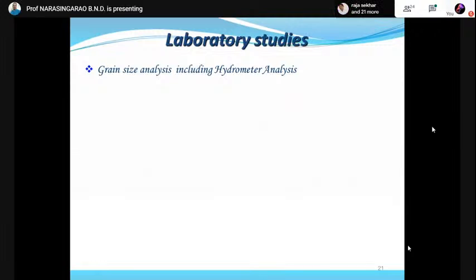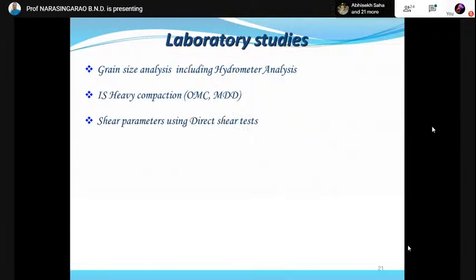The laboratory studies of the fly ash, without adding any admixtures and also after addition of admixtures, have been carried out, which include grain size analysis, including hydrometer analysis, because a major portion of the fly ash is fine material. Heavy compaction, shear parameters using direct shear test, CBR, and permeability have been determined. The shear parameters, CBR and permeability tests have been conducted at heavy compaction.